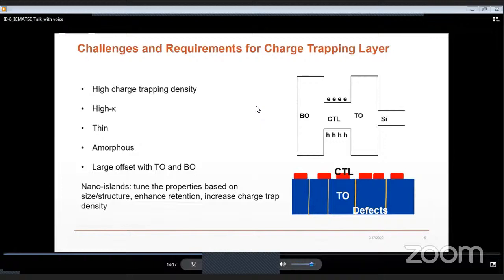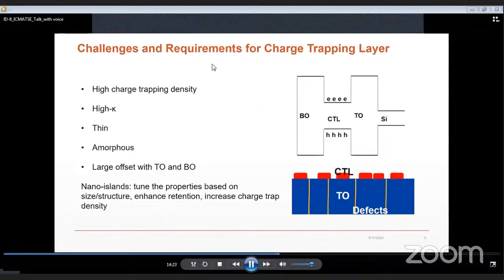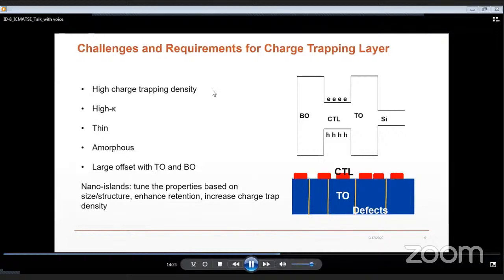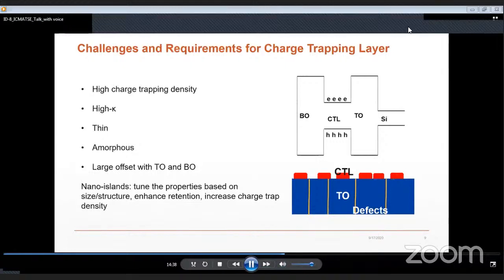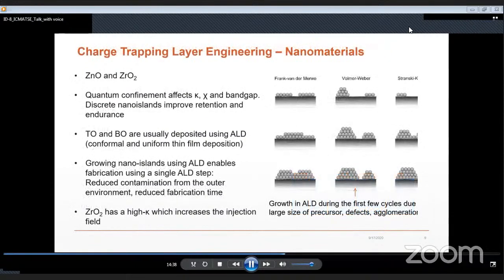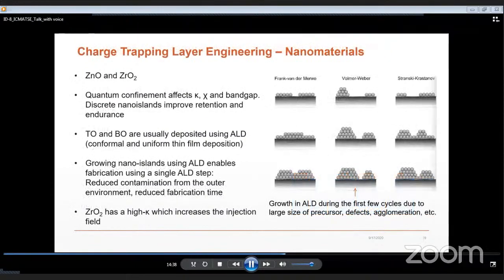For example, using quantum confinement. Quantum confinement allows us to tune the electronic properties of the material. In addition, having discrete nanostructures would enhance the retention, as only the nanostructure above a specific defect in the tunnel oxide would lose its stored charges. To this end, I have worked on the engineering of the charge trapping layer using the atomic layer deposition tool in order to grow nano islands.